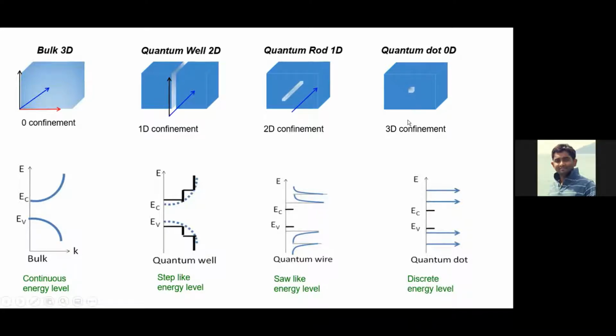And when it comes to quantum dots, scientists say it's zero-dimensional. Why zero dimension? Because electrons cannot move in any of the three directions. In all directions it is confined. That's why it's a zero-dimensional material. It's completely confined, and you can see the energy levels are completely discrete, so you can distinguish the valence band and conduction band structure, and it moves away from the bulk band gap. When you change the size, the confinement changes. So you will have a different gap for the particle, and that's why you will see different emissions.